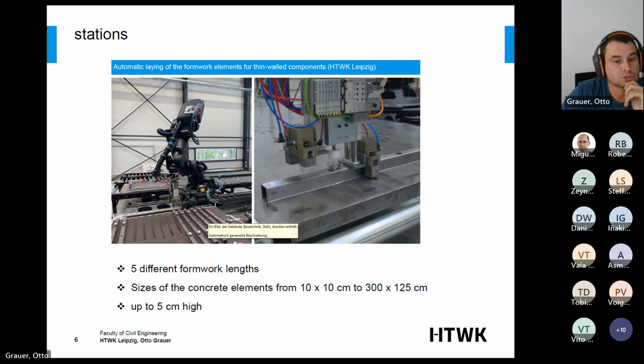Yeah, reduced, and the height of the formwork elements was limited to 5 centimeters. In steel concrete, this is 1 centimeter, but it's too big for textile reinforcement elements. In addition to currently available shuttering robots, the use of 6-axis robots enables the simultaneous insertion of magnetic bar anchors on the vertical sides of the shuttering. These are needed to provide anchorage points when the components are lifted off later.